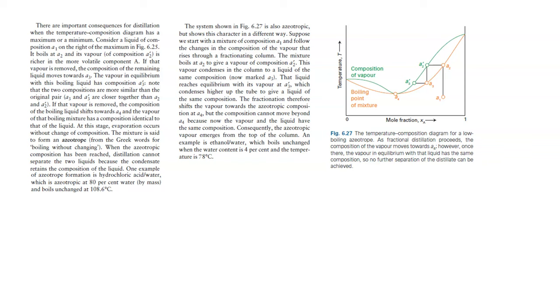Suppose we start with a mixture of composition A1 and follow the change of the composition of the vapor that rises through a fractionating column. So we're starting with A1. The mixture boils at A2 to give a vapor of composition A'2. This vapor condenses in the column to a liquid of the same composition, now marked A3. That liquid reaches equilibrium with its vapor at A'3, which condenses higher up the tube to give a liquid of the same composition. The fractionation, therefore, shifts the vapor towards the azeotropic composition at A4, but the composition cannot move beyond A4 because now the vapor and the liquid have the same composition. Consequently, the azeotropic vapor emerges from the top of the column. An example of this is ethanol in water, which boils unchanged when water content is 4% and the temperature is 78 degrees Celsius.